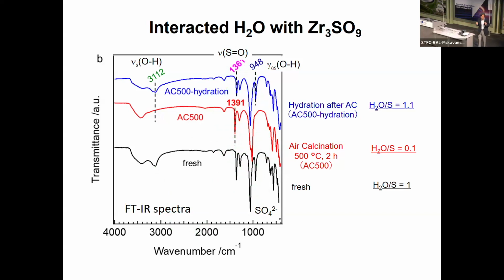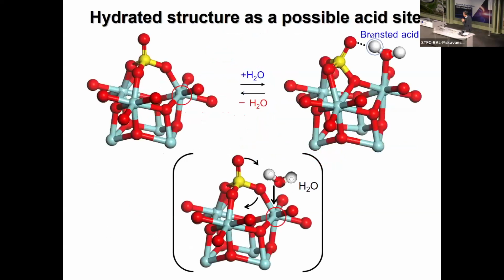So the water is strongly influencing the state of this species on the surface. There must be some interactions between the SO bond and water. That's very simple work. Based on this, of course, we have done a lot of calculation work to support this, but just briefly, this is the initial state. And after exposure, water interacts with this structure, forming this kind of state.